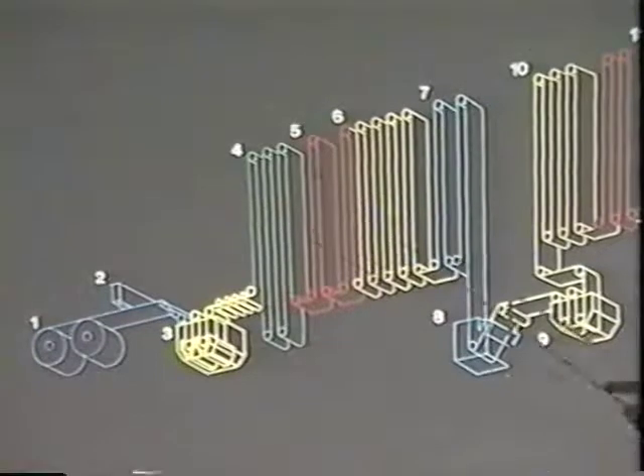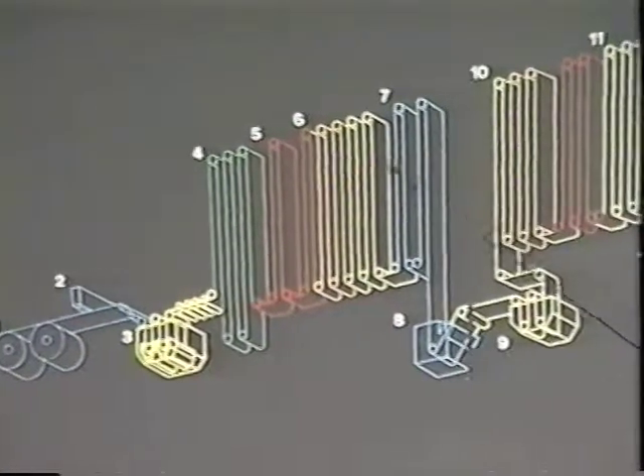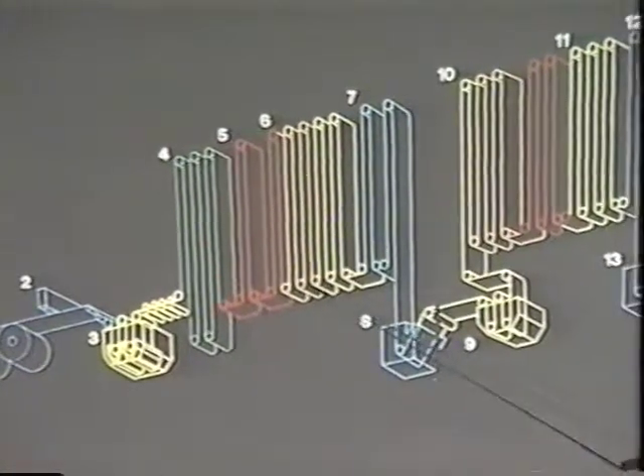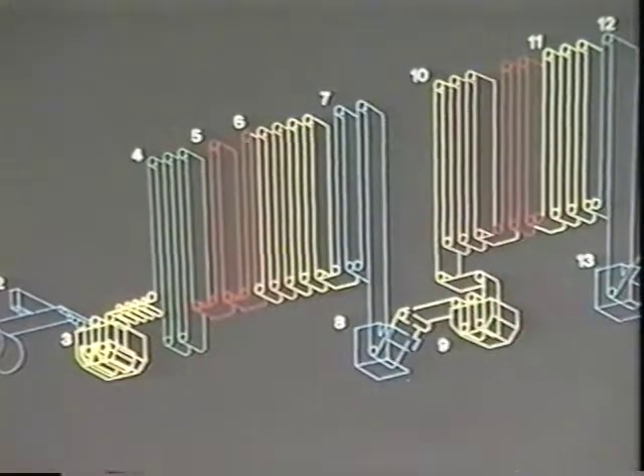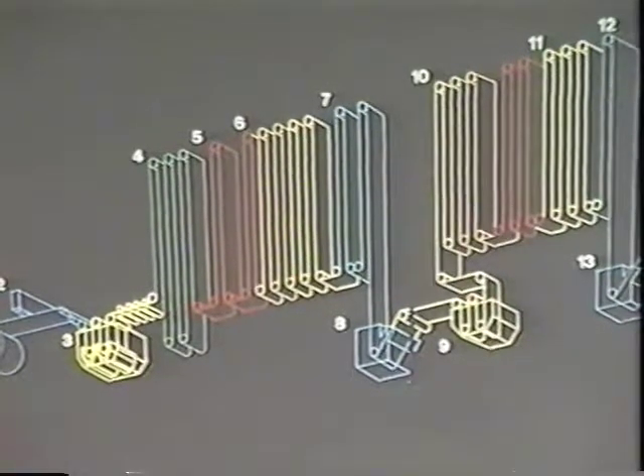We decoil it, we put it through an accumulator, we heat it up through a preheat section, a heat section, and then we soak the little guy. When we soak it, this is the first key temperature. We don't talk about a window here, we talk about a temperature. Depending upon the cycle, the controlling temperature might be 1,300 degrees. Remember in the batch, we said 1,240 to 1,340? Here it's 1,300 degrees. There is a tolerance around that built within the process control, but it's not a 100-degree tolerance, it's about a 30-degree tolerance.